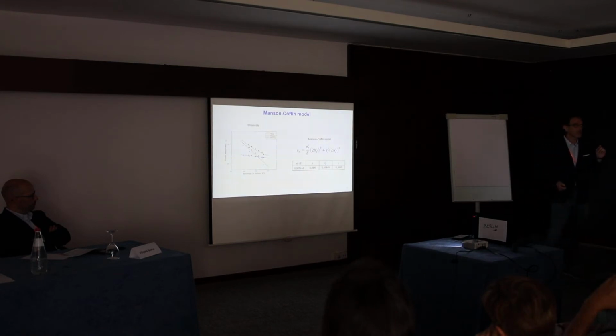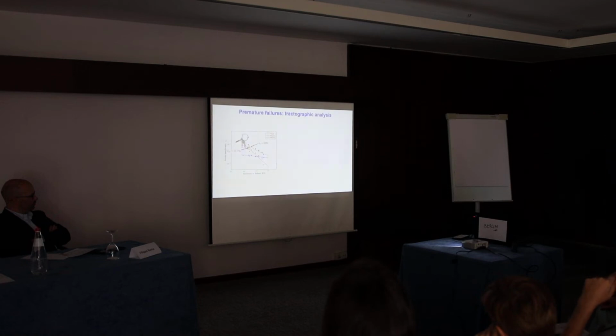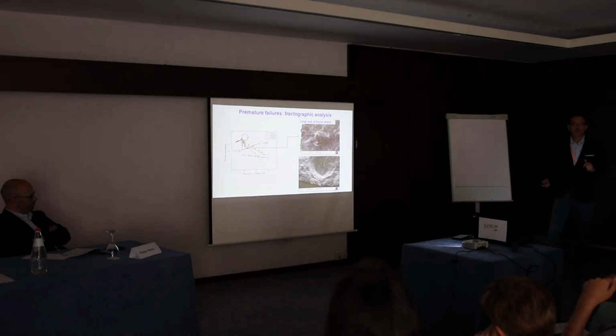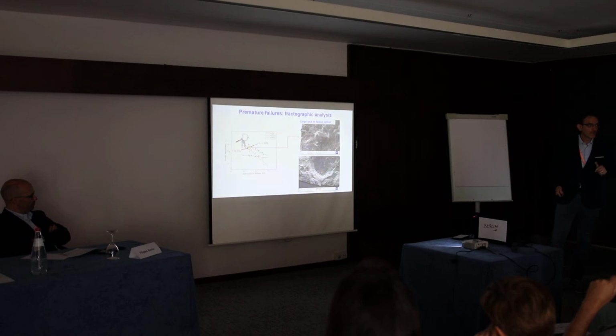So we decided to further investigate this point, tested at 0.7% strain amplitude, because you can see here that this point failed much earlier than the average Manson-Coffin curve, and even earlier than the next point tested at a slightly higher strain amplitude. And we found out, after some fractographic analysis, that the cause of this premature failure was a very large lack of fusion defect in this space.